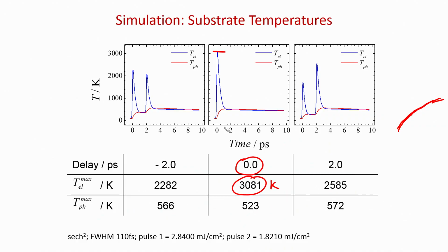This time delay makes it non-equilibrium. Although the electronic bath has the energy and has started transferring it to the phonon bath, maintaining the same temperature for both baths takes some time, almost 1 picosecond,